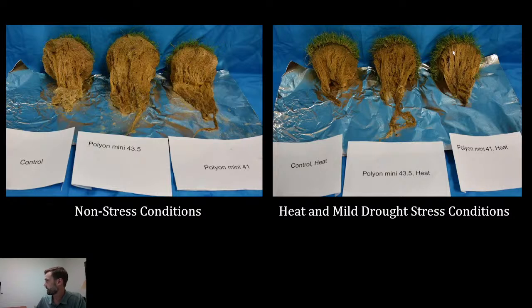So at least in this trial, we were unable to document any negative effects of any of these fertilizer applications compared to the non-treated control. And in the case of 43.5 mini, we had both a positive turf response and we had a positive root growth response under these heat and mild drought stress conditions.